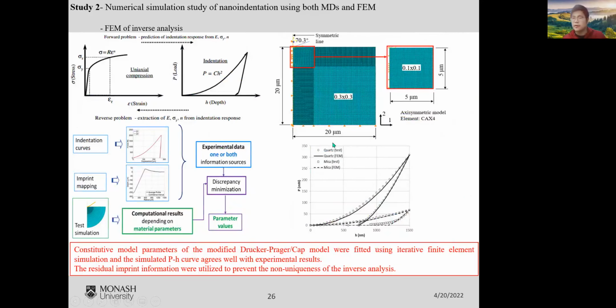Apart from the molecular dynamics simulation, we also carried out finite element simulation because we want to obtain the stress strain curve directly from nano-indentation. So how can we obtain the stress strain curve from nano-indentation? That is, we have carried out the inverse analysis. We used the modified DPCAP model, and we found that the numerical results agree well with the experimental result.